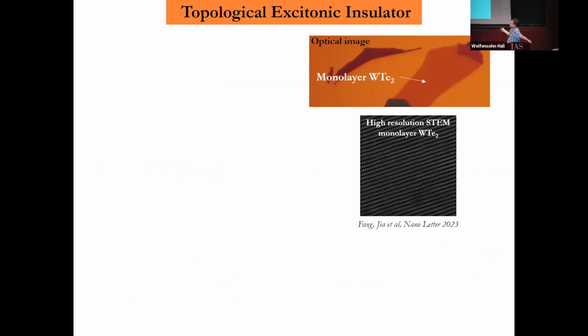So the material in reality looks like this on the optical microscope, and this is the high-resolution scanning transmission electron microscope image, where the white spots are tungsten. What I'm showing you here is exactly what I plotted - the real material, single layer, matches what I was showing you in the PowerPoint.